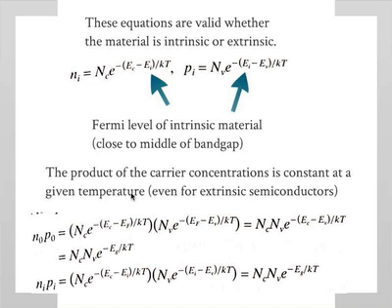In an intrinsic semiconductor, this is clearly obvious, right? And remember, we saw this last class. In an intrinsic semiconductor, N naught times P naught equals Ni squared. Ni is of course fixed. It's a constant. Depends on temperature. So this product depends on temperature, but it should always be equal to Ni squared. So that's what we're trying to do here.